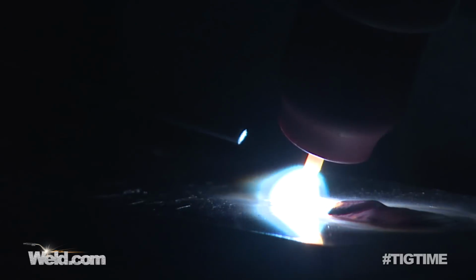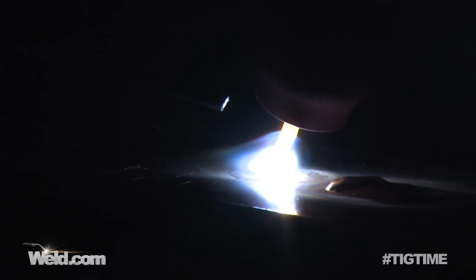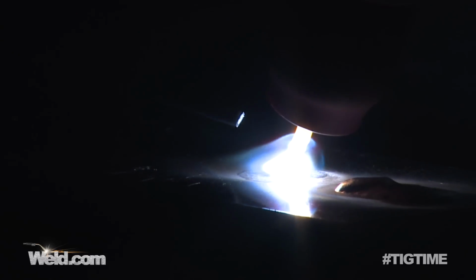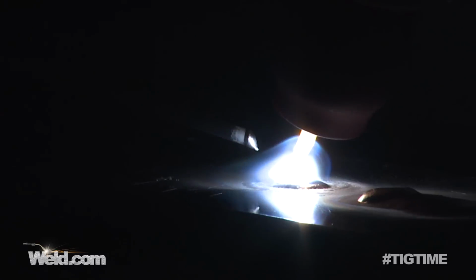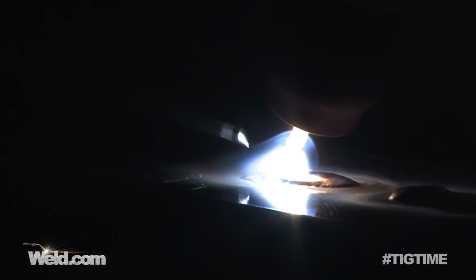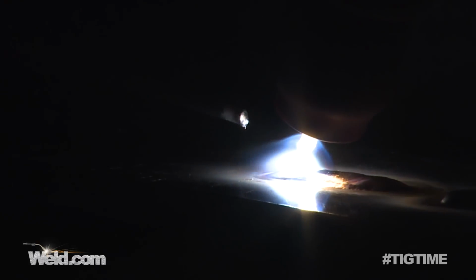Okay, I've exchanged the tungsten. I'm up to a 3/32, getting a lot of cleaning action. I'll reach melting point here pretty soon. Pretty thick material, and you just have to wait for it. Sure enough, there's a puddle starting to form. Anyway, it's wetting out very nicely, and you can see that the point is still on the tungsten. It's not challenging at all. So overall, that's probably the right setting.